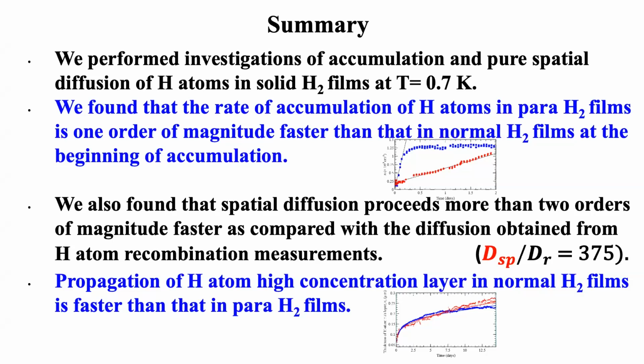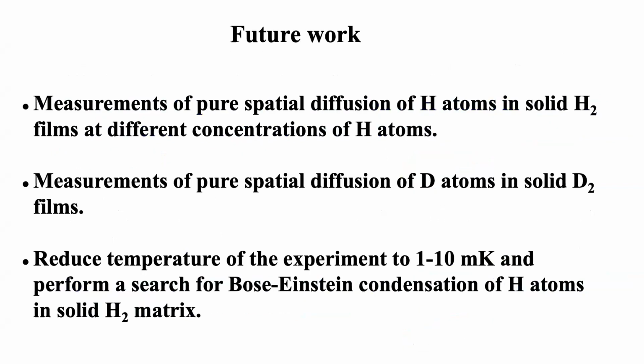We also found that spatial diffusion proceeds more than 2 orders of magnitude faster compared to diffusion obtained from the recombination measurement, as shown by this coefficient. But we also found that propagation of the H atom high concentration layer in normal film is faster than in para-hydrogen, as shown in this curve.